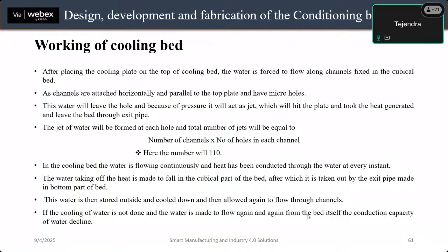So what is a cooling bed? A cooling bed is a cubical shaped environmental conditioning bed designed for metal 3D printing. More specifically, it provides a stable structure for the 3D printing material and also facilitates easy cooling of the base plate. The cooling bed comprises different channels placed horizontally and parallel to the heat bed. These channels feature holes on the top surface so that water can be sprinkled on the top plate during the 3D printing.